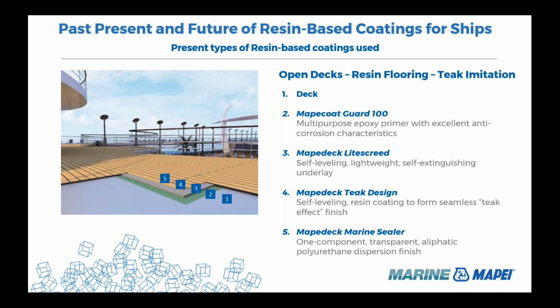Before applying the underlayment, we typically apply an adhesion primer. Like in this slide, you can see that we have applied the MAPEcoat Guard 100 as an adhesion primer. The MAPEdec Light Screed as an underlayment, because this is an open deck. So typically on an open deck, you have a polyurethane system. So the MAPEdec Light Screed is a polyurethane underlayment, on top of which we apply, in this case, the MAPEdec Teak design, followed by a sealer to protect the surface.